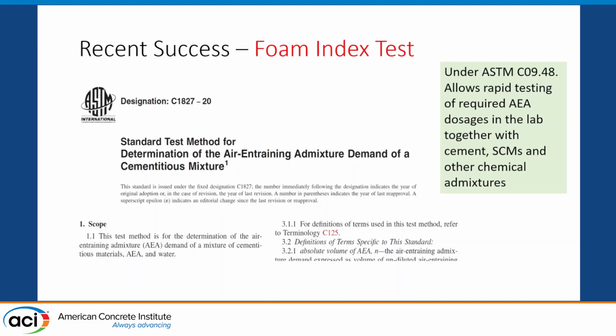One of the things we need is better performance tests, and something that has been developed with a number of people, and Larry Sutter got this through the system, was a foam index test. It's not a new test, but it was originally applied to evaluate loss on ignition in fly ashes. I chair a committee on performance of cementitious systems with chemical admixtures, looking at the whole binder, and this test can be used to evaluate whether you're going to have air entraining issues with a combination of your chemical admixtures and cementitious materials.